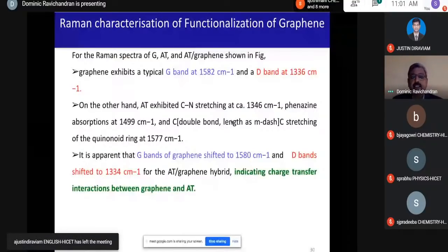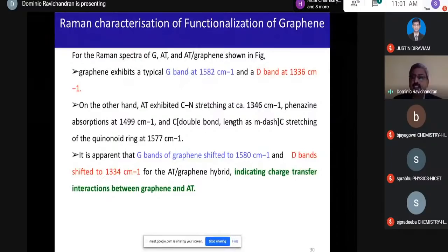On the other hand, the aniline trimer exhibits a CN stretching at 1346 cm⁻¹, phenazine absorption at 1499 cm⁻¹, and so on. It is apparent that the G band of graphene is shifted from 1582 cm⁻¹ to 1580 cm⁻¹, and the D band shifted from 1336 to 1334 cm⁻¹, indicating a charge transfer interaction between graphene and AT because of the pi-pi stacking.